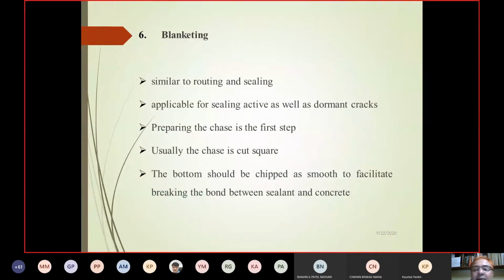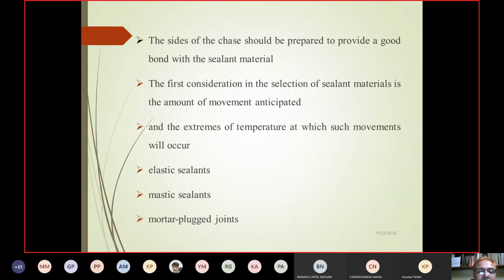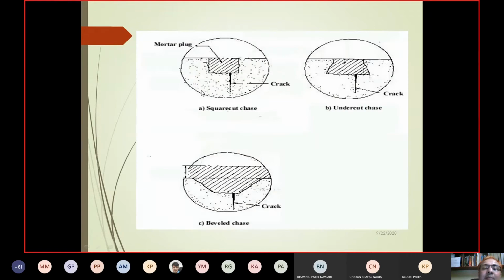Blanketing means jacketing. Okay, this is the blanketing. If we are not going for a V groove in expansion joints and various other joints, this gives more contact area to the material, more surface area, spherical. This undercut doesn't allow the material to come out and release the crack. If you want to go for more material, then we have to go for the beveled shape and it will go in like this. But in most cases, type 1 and 2 and V groove we are using.